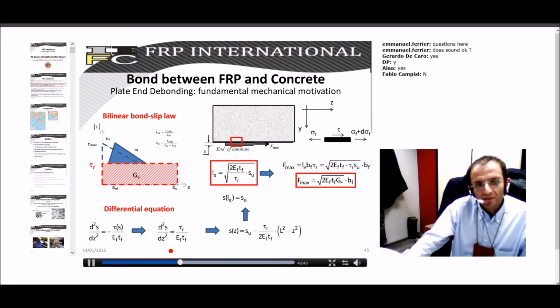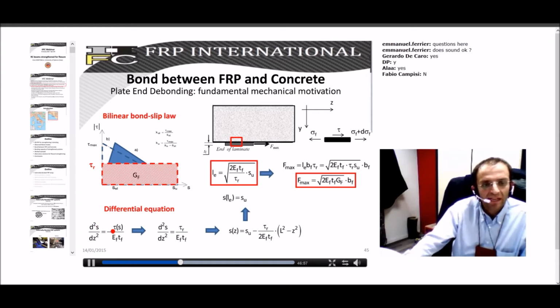But now, let's try to understand which are the parameters actually controlling LE, and we can do it by going back to our equations and modifying them in this way. If you remember the previous slides, you had here Ks, but this was true only in the elastic range. Now we have to write tau as a function of S, generally speaking. If we introduce a very simplified shape of tau, so if we imagine just for a while that the relationship between tau and S is just a constant value of tau up to a maximum SU. If you mobilize, for an infinitesimal value of S, tau R, and then you have this constant value up to failure. So you have a constant value.